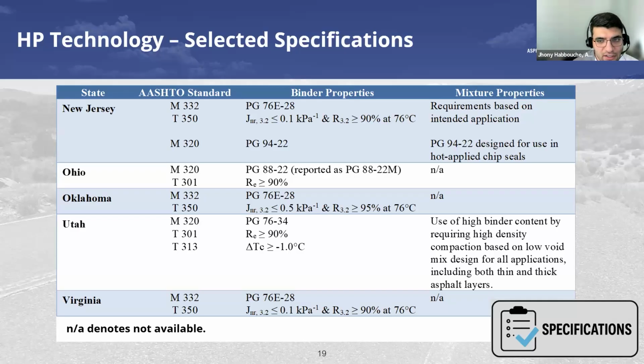So this is a way of doing HP mixtures by just binder swapping. Well, in the case of Utah, for example, first of all, they use an M320. Their PG is a 76-34. They only have requirements on their percent recovery, minimum 90 degrees C, minimum 90 percent, and then they have some requirements on additional parameters like delta Tc.